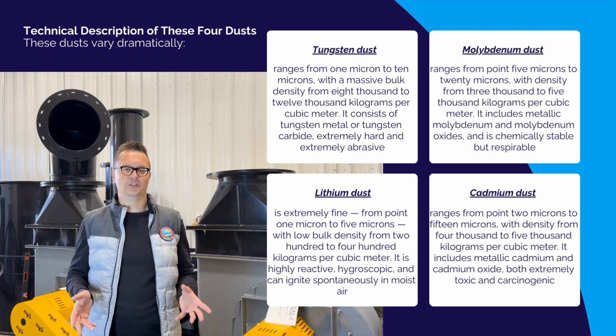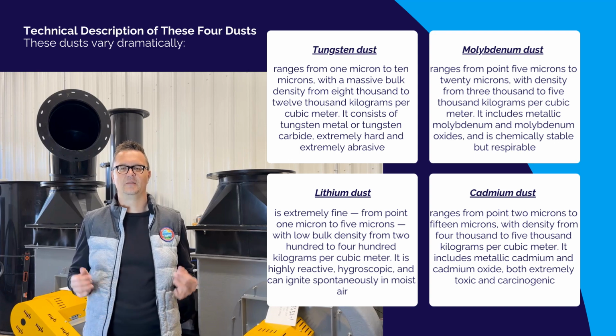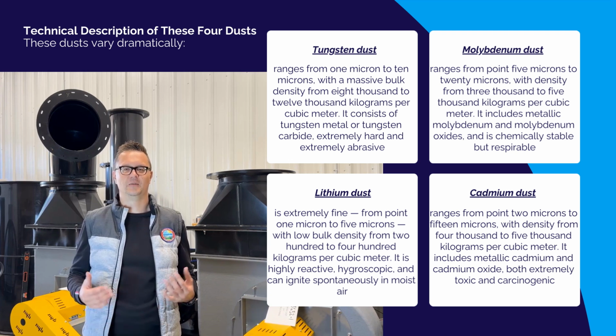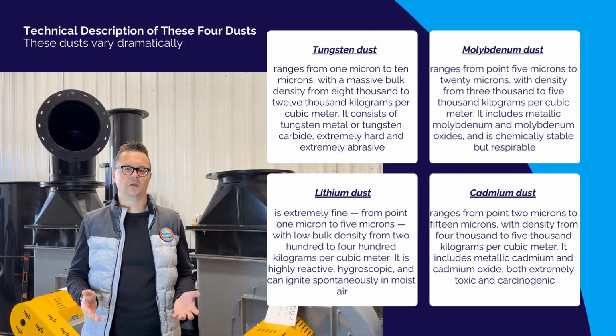Technical description of these four dusts. These dusts vary dramatically. First, tungsten dust ranges from 1 micron to 10 microns, with a massive bulk density from 8,000 to 12,000 kilograms per cubic meter. It consists of tungsten metal or tungsten carbide, extremely hard and extremely abrasive.